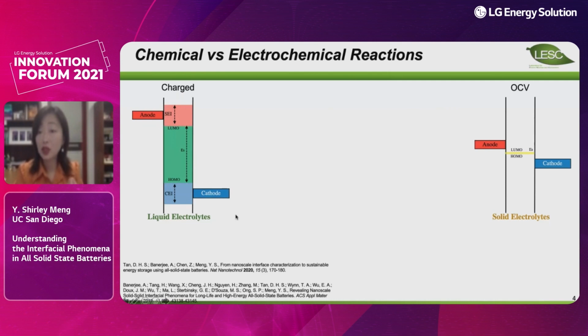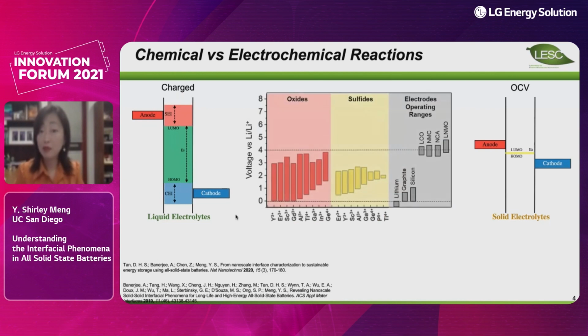In terms of the solid electrolyte, particularly when we choose sulfide-based electrolyte, one will ask, why would we choose sulfides? Because the stability window is so low, right? Sulfides also have another challenge, which is that they are chemically incompatible with the NMC or LiCo cathode materials.